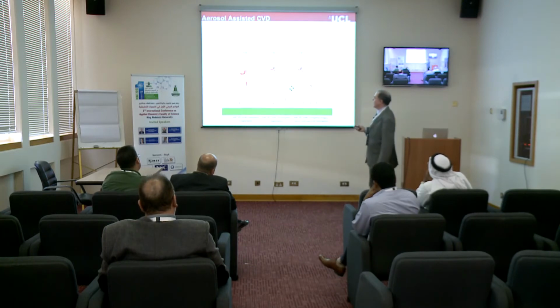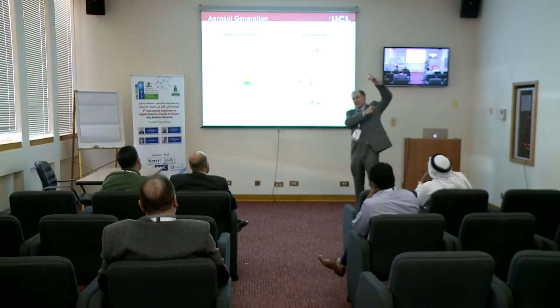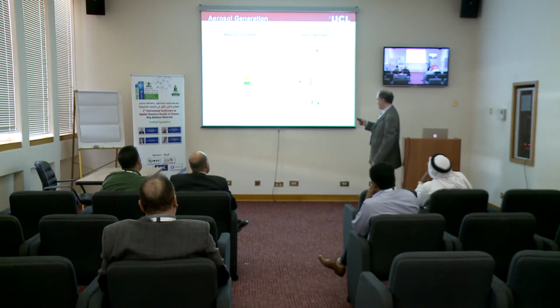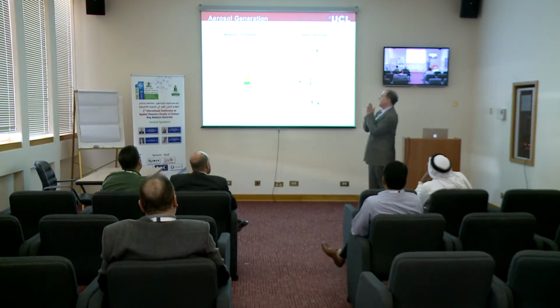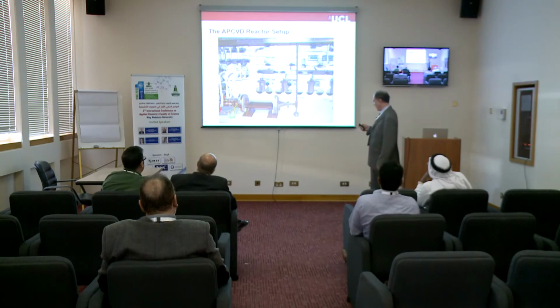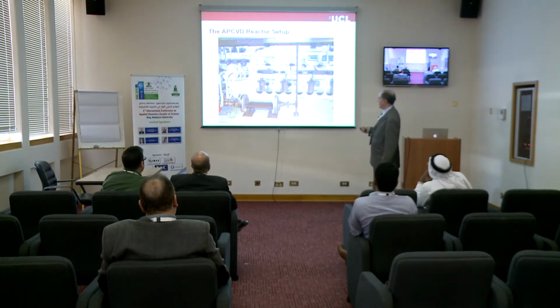is manufactured. In particular, we've looked at a process called aerosol-assisted CVD, where we use an aerosol as a delivery vector for our starting materials. And there are 2 ways in which we do that, either with an ultrasonic humidifier or with a collision atomizer. In fact, if you've had a little spray this morning, you would have used something which generates an aerosol. That's essentially what comes out. You have an aerosol gas. But we use this aerosol. So we pass gas through the aerosol, we transport the aerosol droplets to the reactor where the aerosol evaporates and we generate our thin film. These are a representation of what our apparatus looks like.